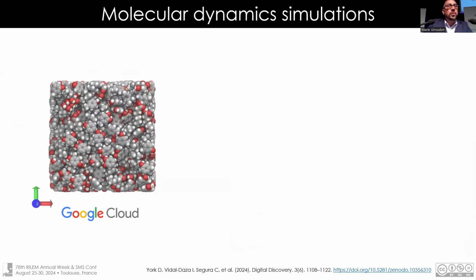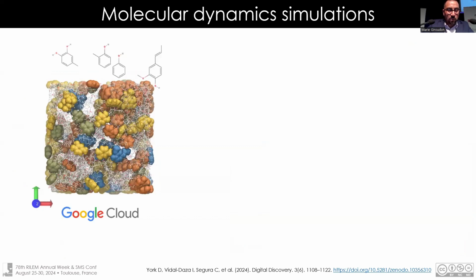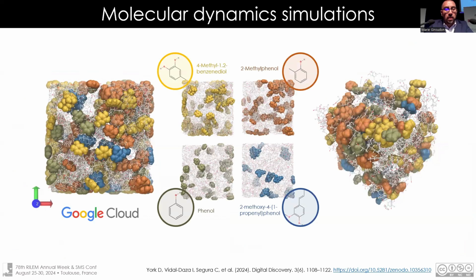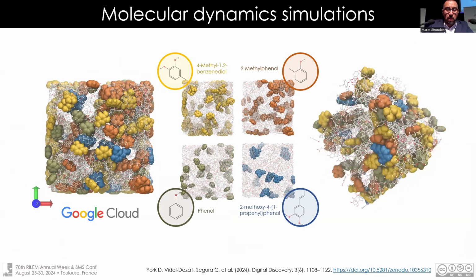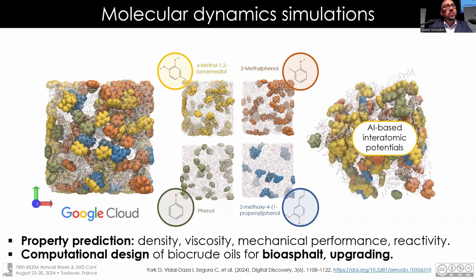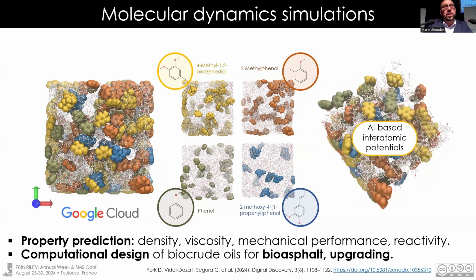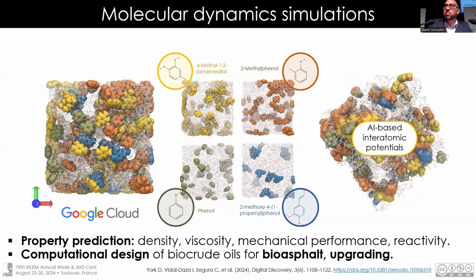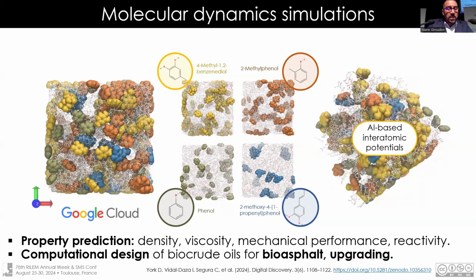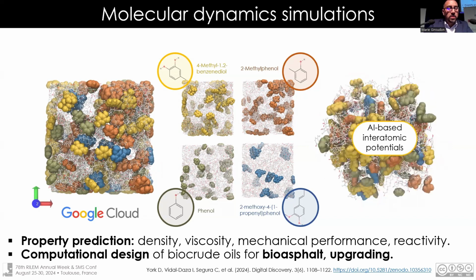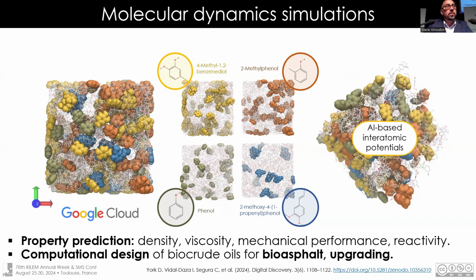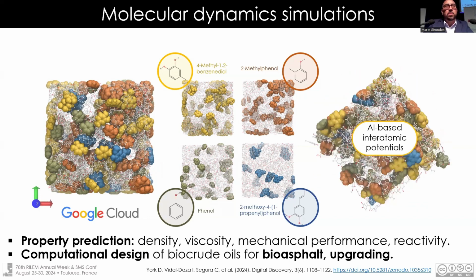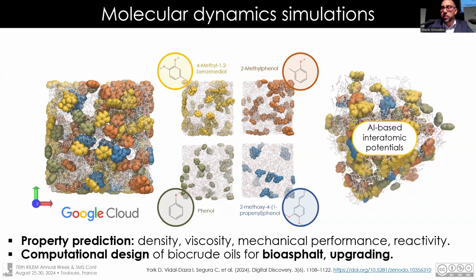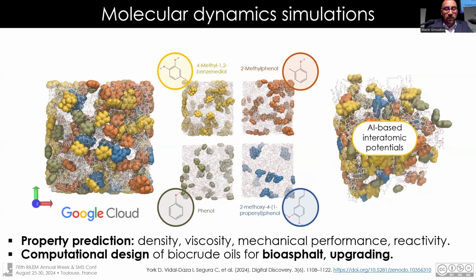On the Google Cloud, it's possible to simulate these specific materials. For example, in this approach, if we isolate only the phenolic component inside the bioasphalt, let me show you. And basically, we can use the molecular dynamics simulations combined with different technology, artificial intelligence, to evaluate the interatomic condition inside the material in order to obtain the perfect bioasphalt to replace the bitumen based on petroleum. It's possible to do property prediction: density, viscosity, and other properties. It's possible to design a computational approach to replace the normal bitumens because we have, for example, in RILEM, a very big commitment in order to reduce the emissions for the future. That's possible and necessary.